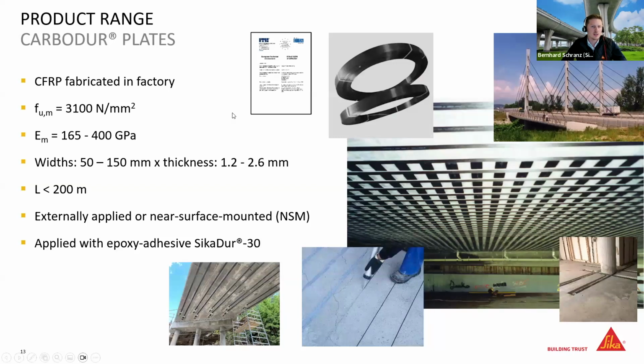So when we go through the standard solutions that are there at the moment, what you will usually use is CFRP plates that you have on a roll. This is fabricated in the factory, and you have all sorts of stiffnesses usually available and different cross sections as well, and you define those depending on the load and surface needs that you have. Usually you bond them externally, like you see here on that bridge, or you can also have them in a near surface mounted configuration, where you have a smaller cross section that you embed in a groove. What you can also do is pre-stress them. So in some cases with very high demands, you can post-tension them and also increase serviceability considerably and also utilize the material even higher. And they're usually glued to the surface with an epoxy resin, which we call Sikadur 30.